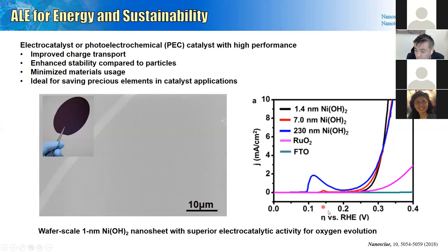Our first work is done using nickel hydroxide. This is a very simple work. We just apply our approach to grow this nickel hydroxide, not really oxide, nickel hydroxide, 1 nanometer sheet. It's a mixture between amorphous and nanocrystalline. Actually, this is a better geometry for the catalytic application. We can make it very large and cover the entire wafer surface, and this showed very nice